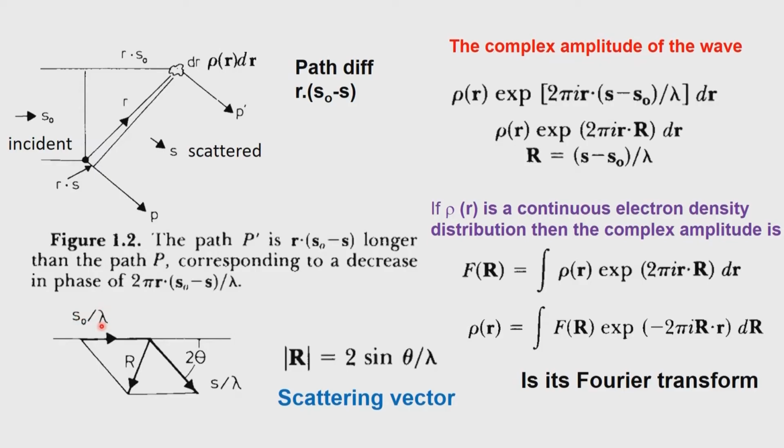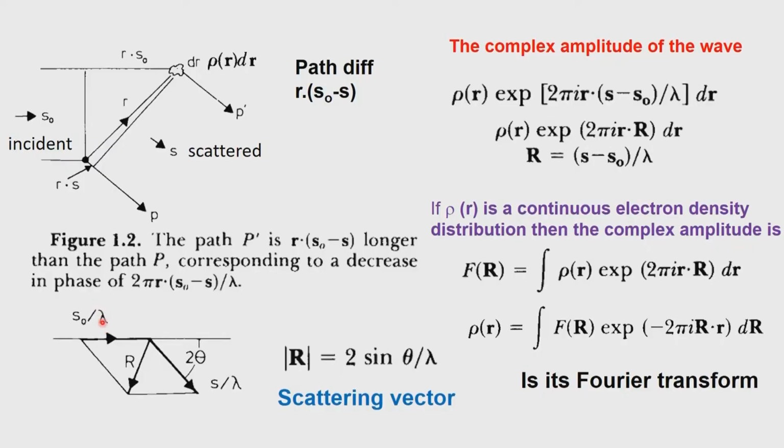Remember that we are talking about atom sizes of the order of 1 angstrom. So, the wavelength can be anywhere between 0.4 to 2.5 angstroms. If we use that wavelength, we will be in a position to see the details associated with atoms and molecules and so on. So, we prefer to use X-rays in that range, about 0.5 angstroms to 2.5 angstroms. Since lambda is coming up as a normalization factor, it is recommended that we use a single wavelength. So, at this particular stage, I can introduce the way in which we generate X-rays.